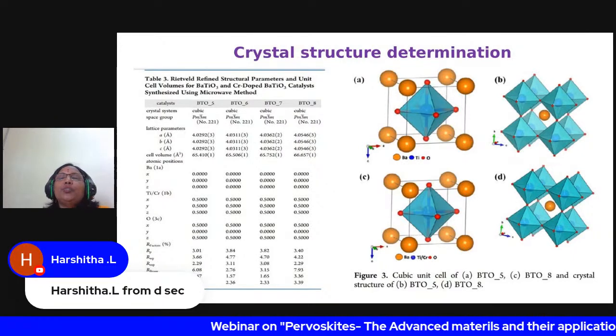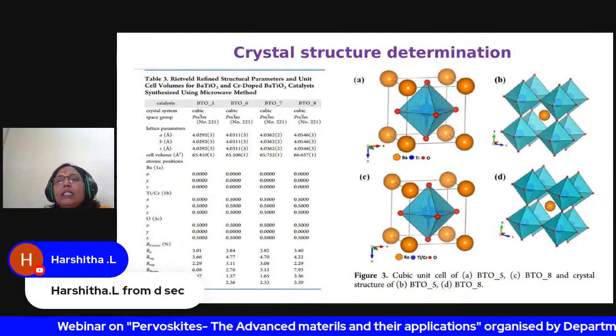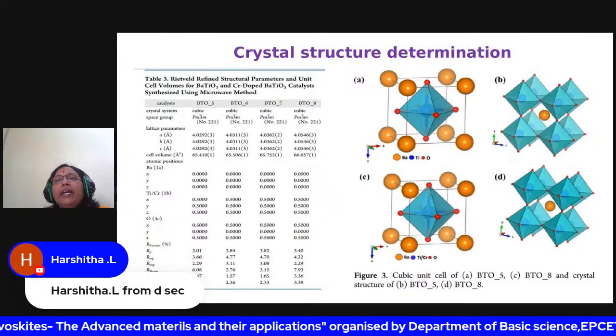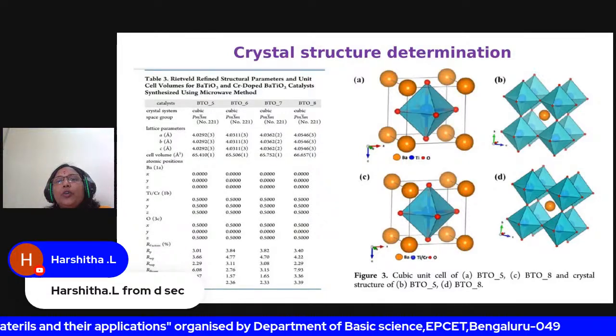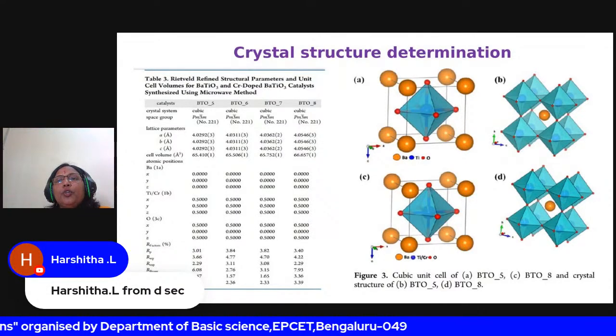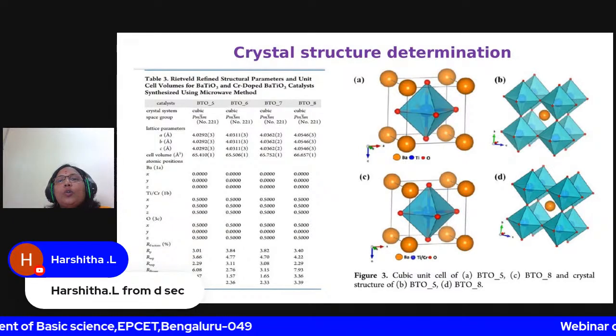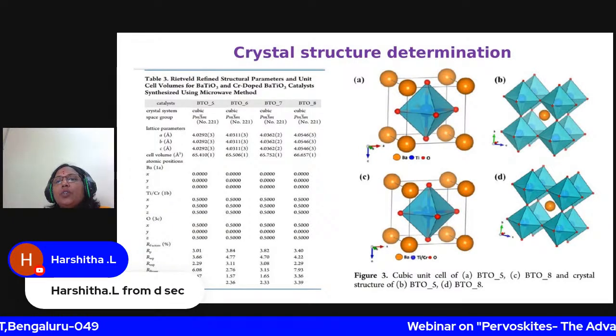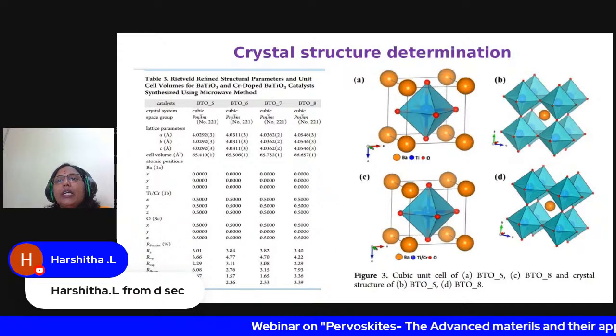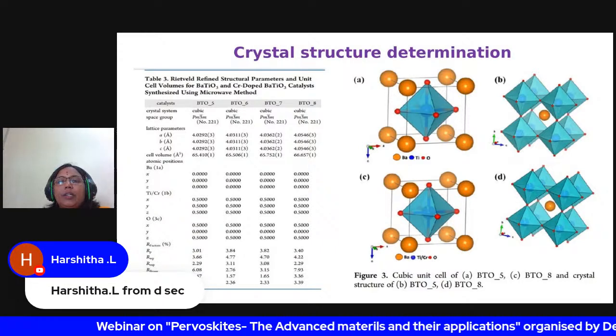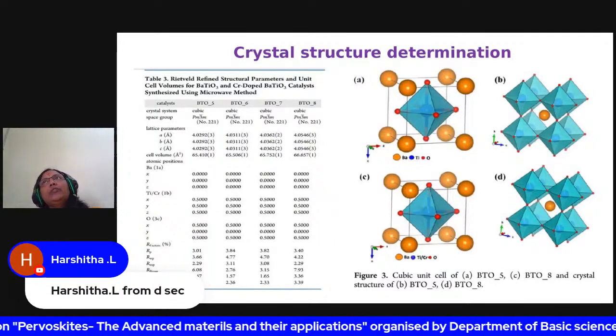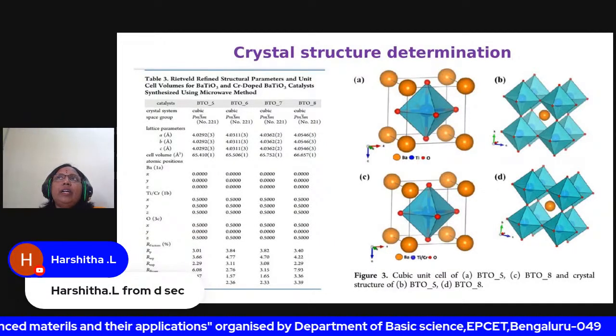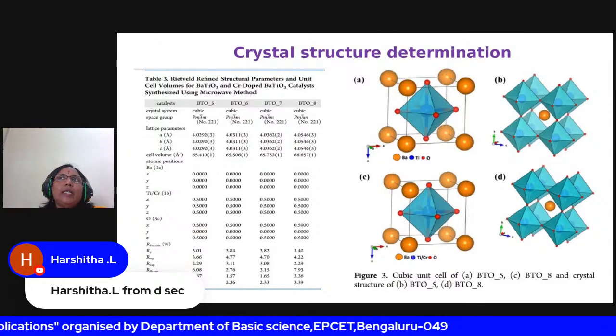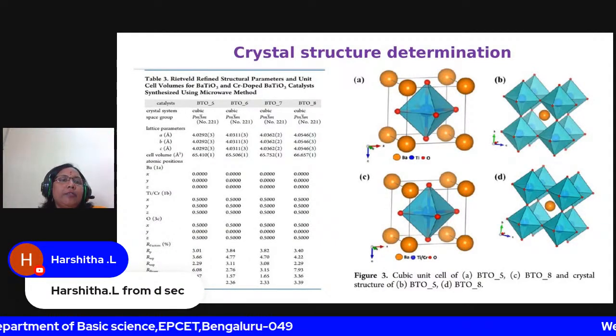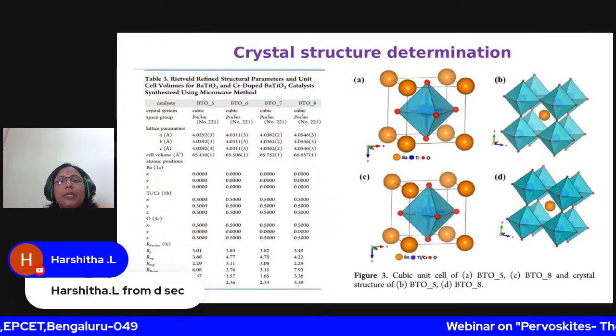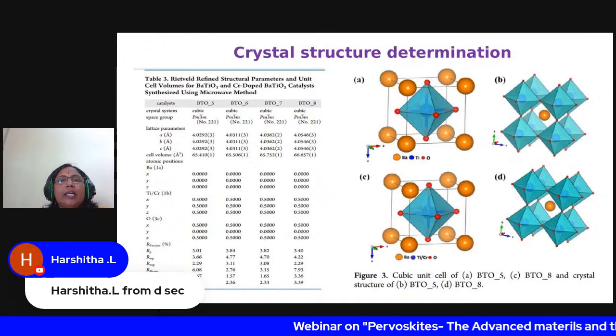We can predict the structure using another program called VESTA. So these are the structures calculated or predicted using that program. In that, this is the unit cell where barium is present at the 8 corners of the cube, titanium at the body center, and oxygen at the face center. This is also regarded as barium having 12-fold coordination and titanium having 6-fold coordination. So we have further confirmed theoretically through Rietveld refinement analysis that the conventionally synthesized materials exhibit the tetragonal barium titanate phase, whereas microwave synthesized samples exhibit the cubic barium titanate phase.